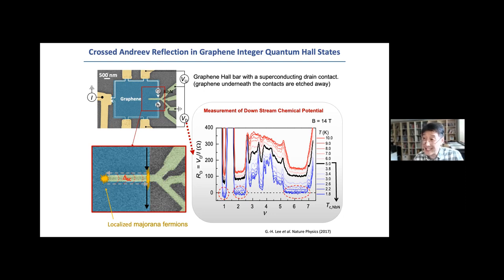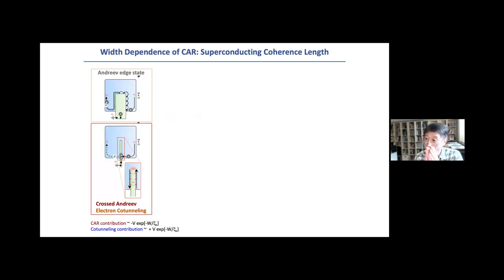How do I know that this is really the case? One way you can test that out is basically varying this width of the superconductor, right? Because we know that the superconductor needs to be thinner than the superconductor coherence length to provide the cross-Andreev reflections. If indeed we make the superconductor thicker and thicker, we expect to see that the signal will quickly go away.